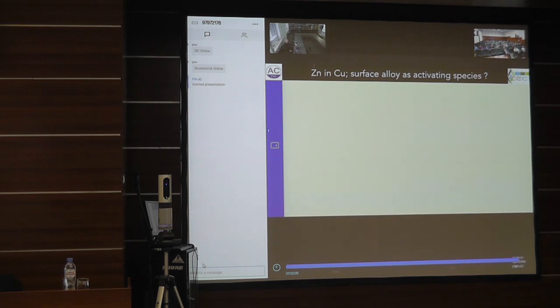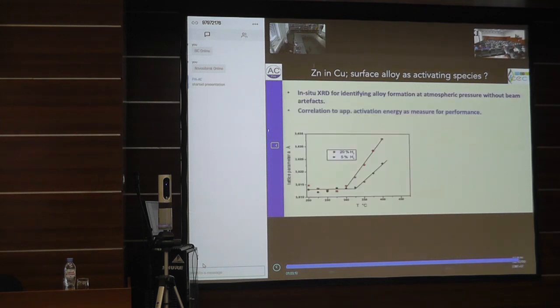Then the last issue is, why is this not brass at 50 bar pressure? Now it could be brass. And then we did an experiment for that. This is operando catalysis in an X-ray diffractometer. And then you see, if you keep the reaction temperature above 300 degrees, you see a non-isothermal increase of the lattice constant because you do form brass at 300 degrees.